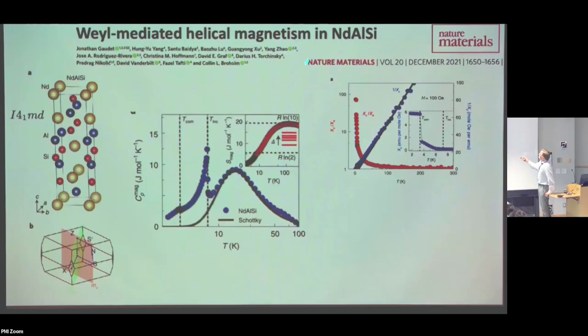Let's see, then in the susceptibility, we see that there's quite large anisotropy that develops as we cool below the temperature of this Schottky anomaly. And that's as we expect, because as we depopulate the excited crystal field levels, we bring out the intrinsic anisotropy associated with the Kramers doublet ground state. And so that begins to increase the ratio between the A and C susceptibility as we come to low temperatures. So this is an easy axis system. The spins really like to be along the uniaxial C direction.